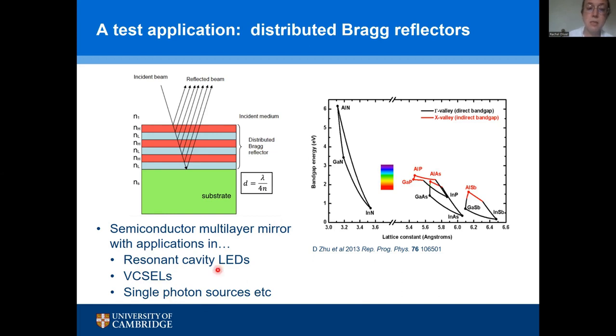Okay, so a distributed Bragg reflector is just a multi-layer of alternating layers of high and low refractive index material. Our high refractive index material is going to be gallium nitride, and our low refractive index material will be porous gallium nitride. And the period of that stack, we want to match it to a quarter of the wavelength of the light we wish to reflect, where it's the wavelength in the material, so normalized through the refractive index. And that then gives us constructive interference between light beams reflecting off each of these different interfaces, and gives us a strong reflection at that particular wavelength.